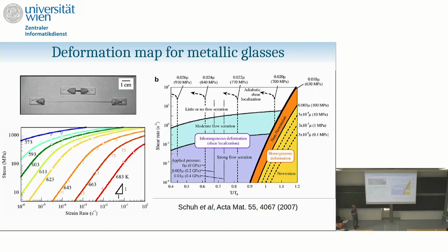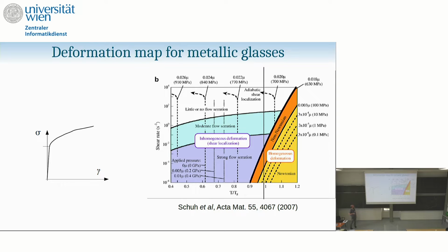What I like about this map is that on the same map you see the plasticity of a solid, the Newtonian behavior, and the non-Newtonian regime. If you take a cut through this map and plot the stress versus strain rate, you see a Newtonian regime and a shear thinning regime, so you would say you have a shear thinning fluid. If you take a cut here, you could not really do tests as a function of strain rate; at different strain rates you would see brittleness and the system reaching failure.